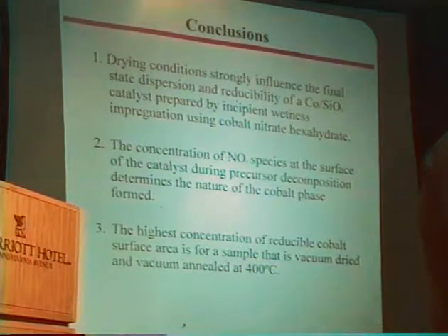And this was somewhat surprising because typically in heterogeneous catalysis literature, they do give a detailed description of how the catalyst is mixed and how the cobalt is deposited, but they do not discuss in detail how it was dried. They say the catalyst was dried, or the catalyst was dried in vacuum, but they don't state the actual conditions that those were, and those seem to have a profound effect on the available cobalt.